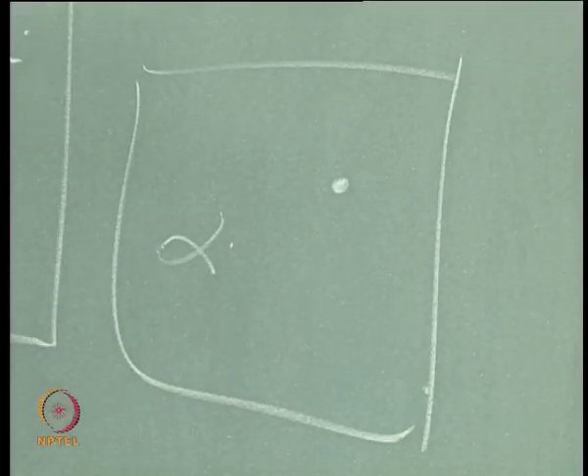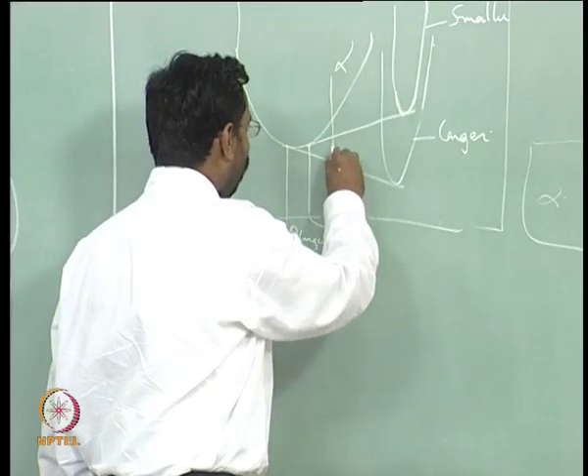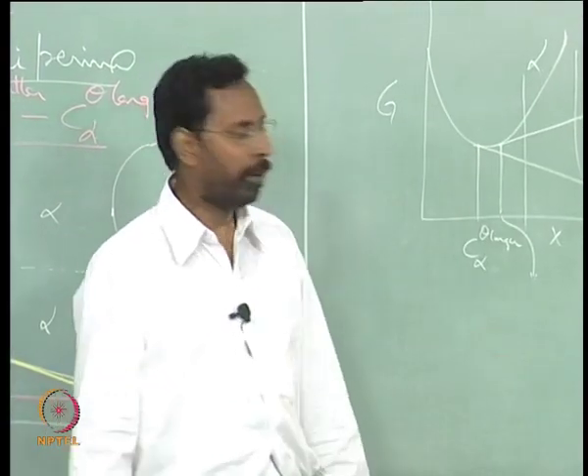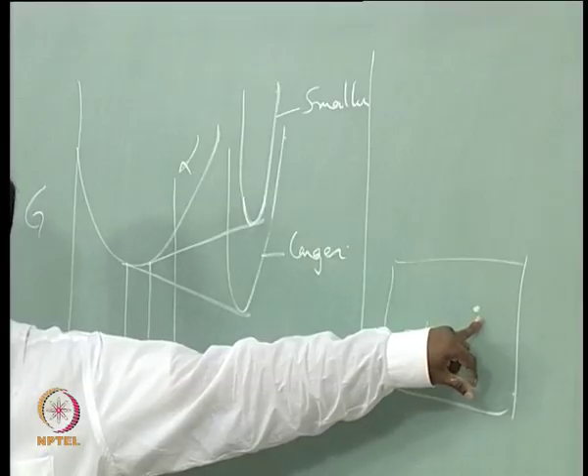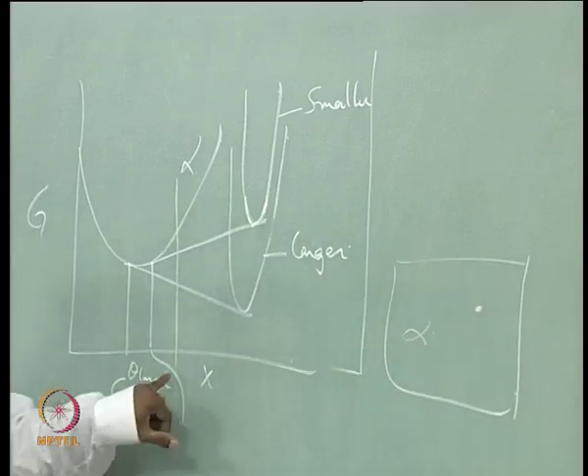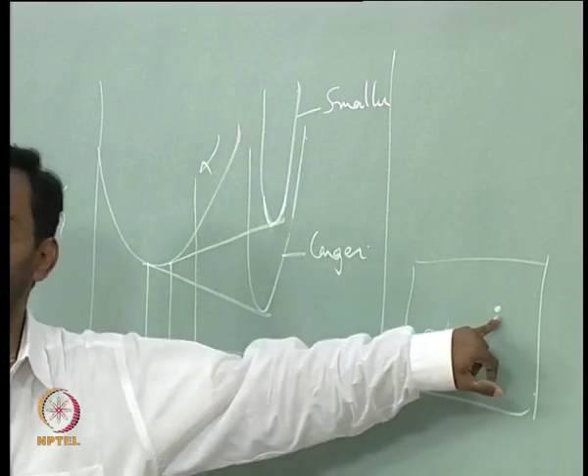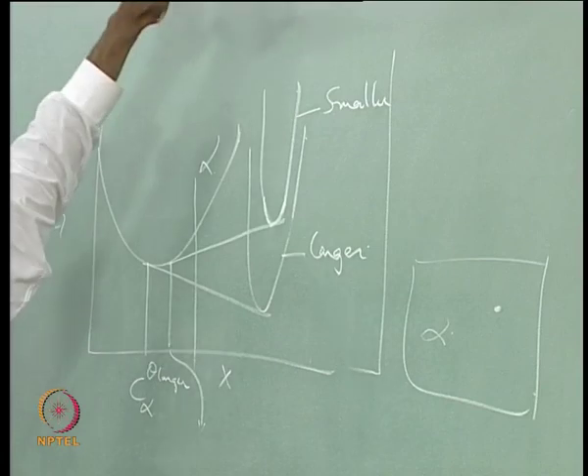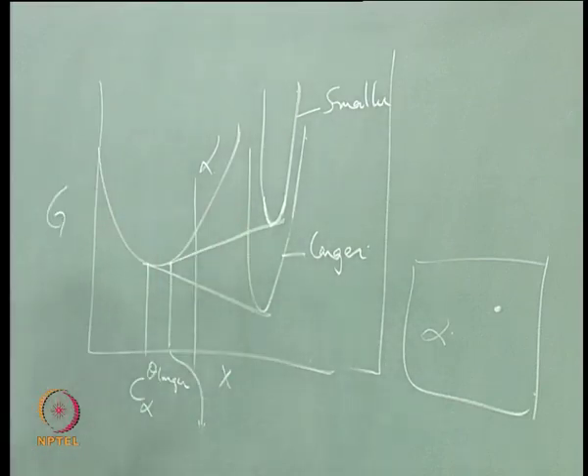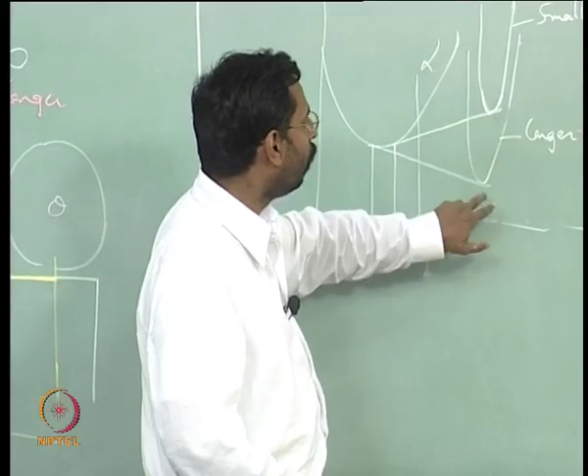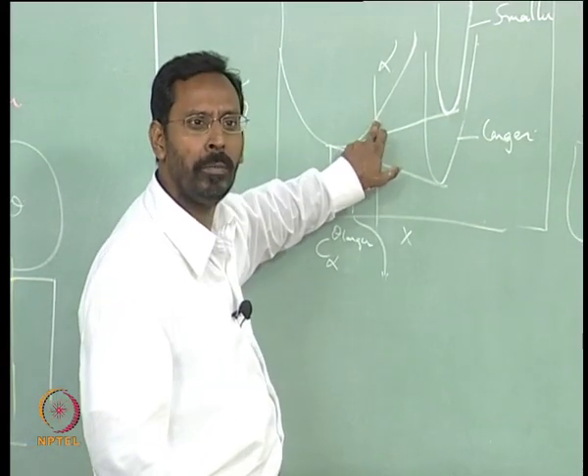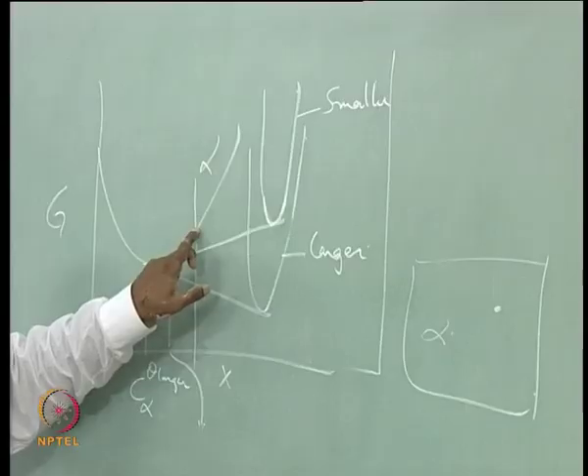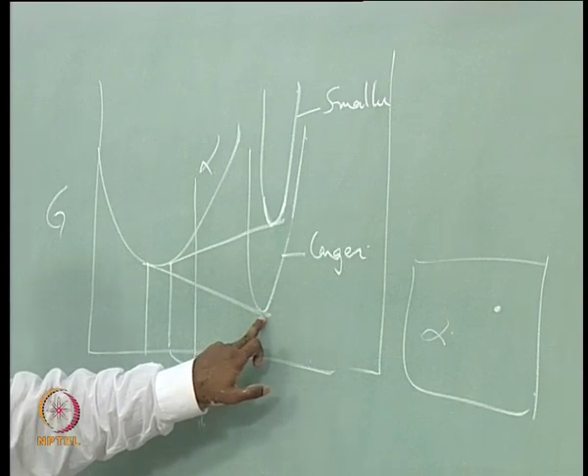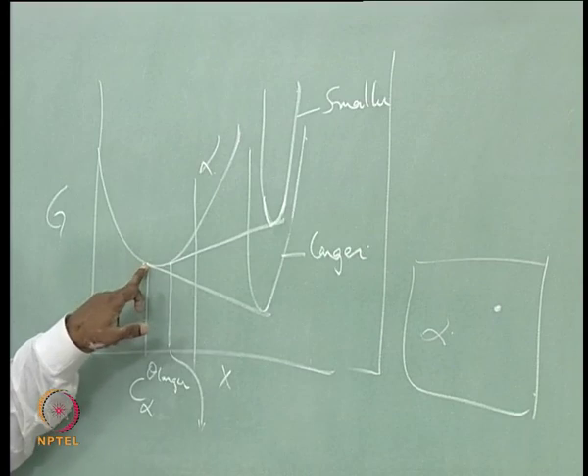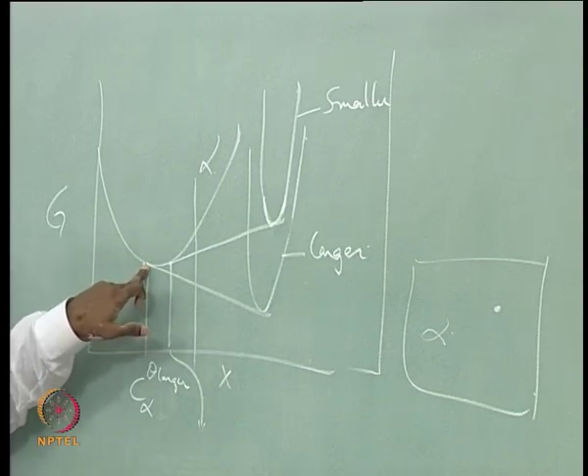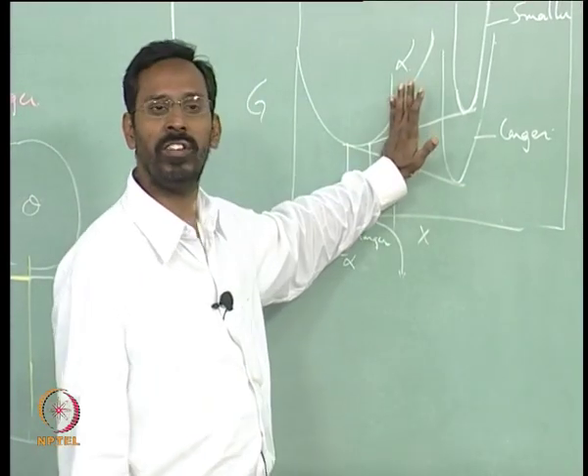The starting alpha that you have is this alpha, am I right? That is 4% copper. The moment a theta is precipitated inside the alpha, the alpha which can be in equilibrium with the theta is not this alpha. This 4% alpha cannot be in equilibrium with theta. Why? Because if I forget about the smaller particle and look at the larger particle as the equilibrium particle, you cannot draw a common tangent between this point, alpha of that composition, and the theta. The only equilibrium that you can have is with the theta and some other alpha, and that is what we call the composition of alpha in equilibrium with the theta,